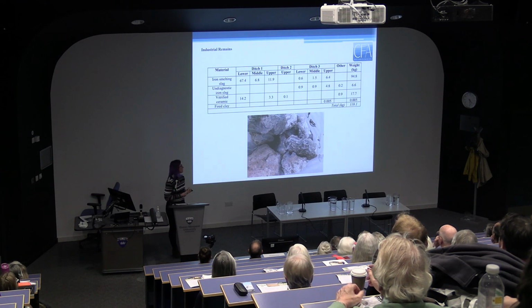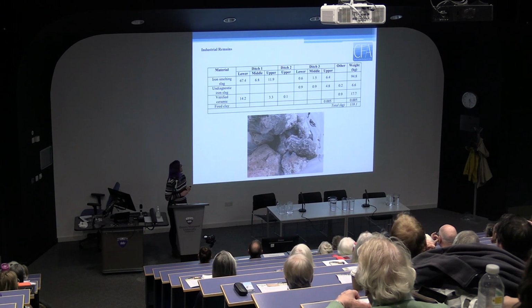Then onto the main material recovered from the site, the industrial assemblage. Nearly 120 kilos of vitrified material was recovered in total, indicating large-scale ironworking. As you can see from the numbers, most of this comes from ditch 1, with smaller amounts from ditch 2 and ditch 3. Most of the material has been identified as iron smelting slag.